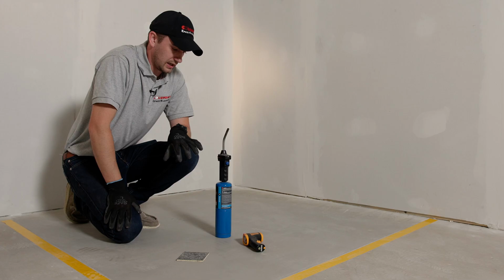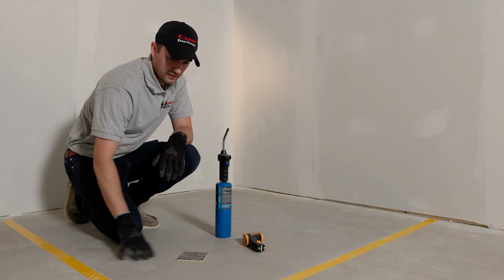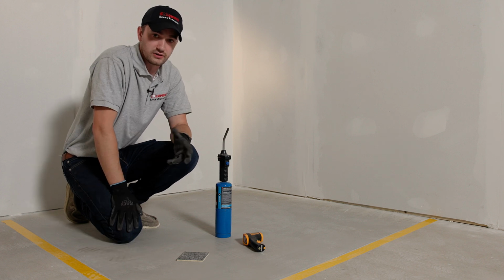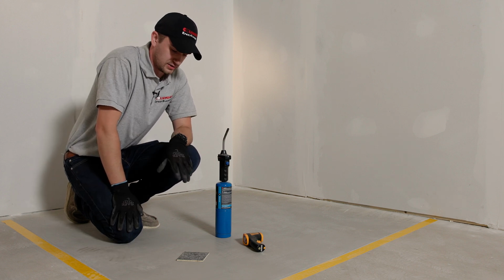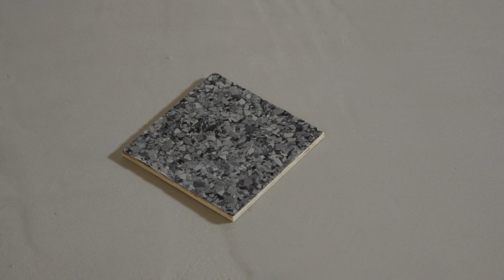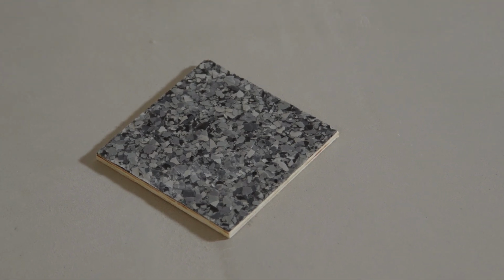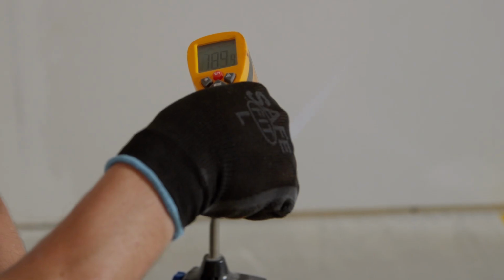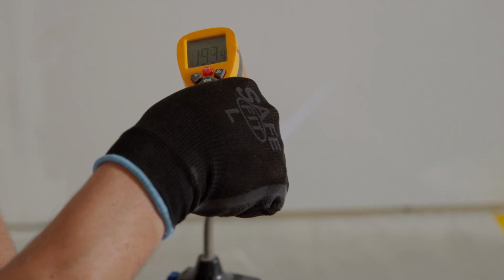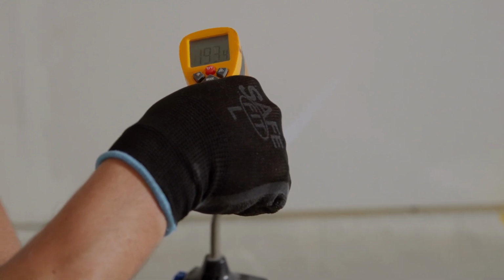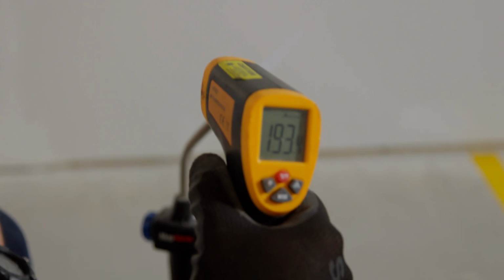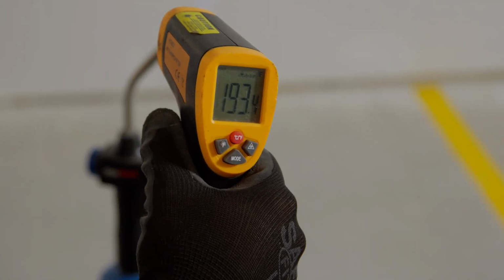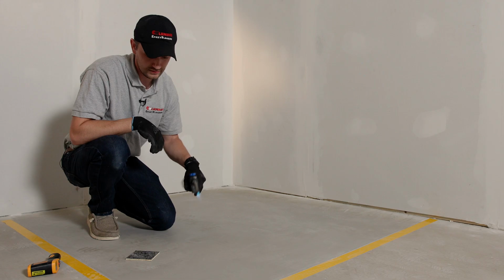We're gonna go ahead and demonstrate that here very quickly. We're gonna take a blowtorch to the sample here, the sample I'm standing on, which is urethane cement, and then we'll take it to just a regular epoxy flake floor with a poly aspartic top coat. For our temperature here on this blowtorch, we're running close to 200 degrees Fahrenheit. So we're gonna go ahead and take the blowtorch to the floor now just to show how the urethane cement reacts to it versus a lot of other traditional epoxy flooring systems.